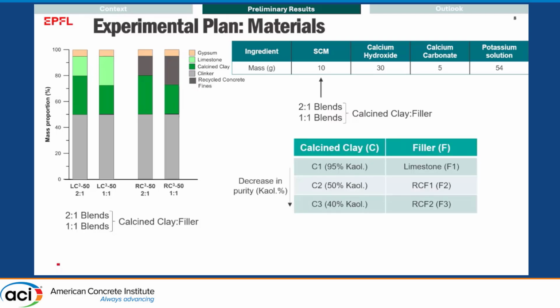Another variable that we try to vary is the clay kaolinite content. As you can see, 3 clays were used, C1, C2, C3, with different percentages of equivalent kaolinite content. Clay 1 has the highest kaolinite content, and it refers to higher reactivity compared to clay 2 and clay 3. And the fillers are limestone and 2 recycled concrete fines. So we have 3 clays, 3 fillers, 2 blend ratios. In total, 18 mixes were tested for the R3-Reactivity test and mortar compressive strength.